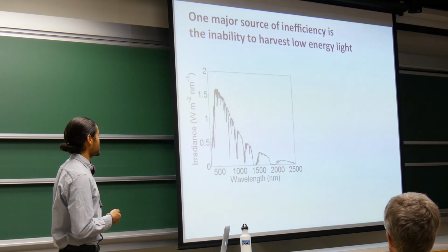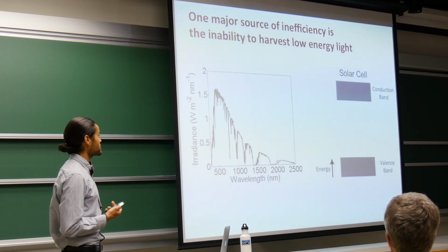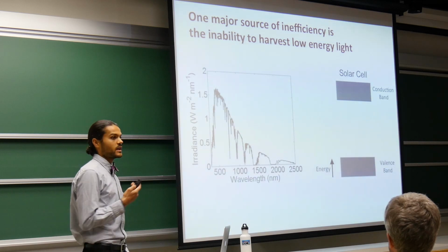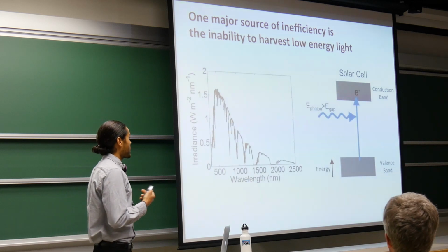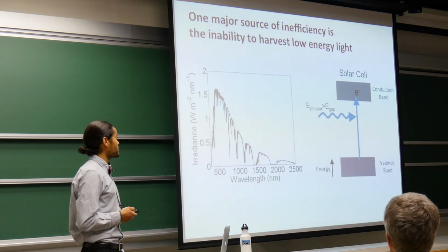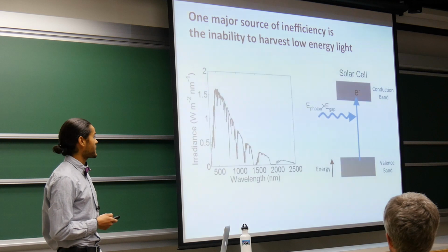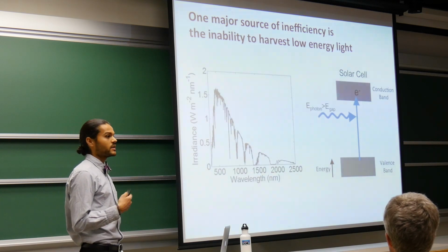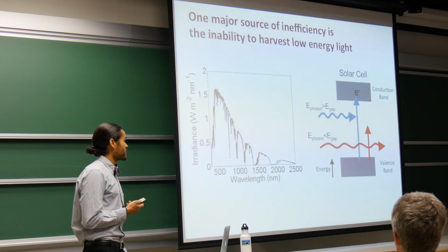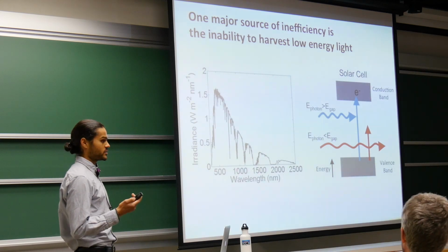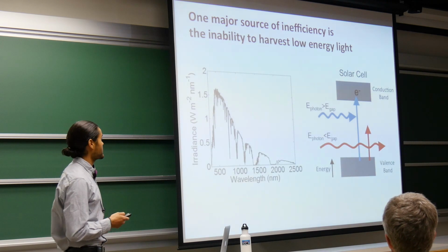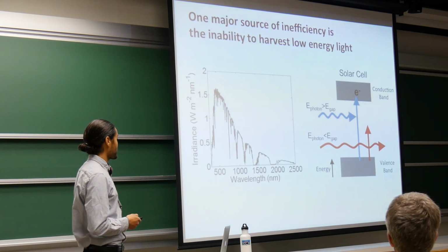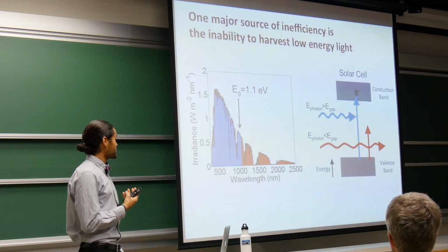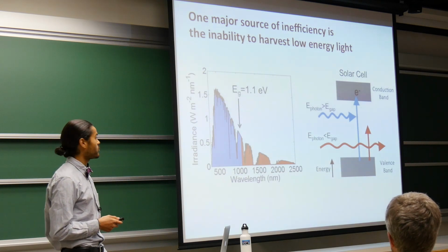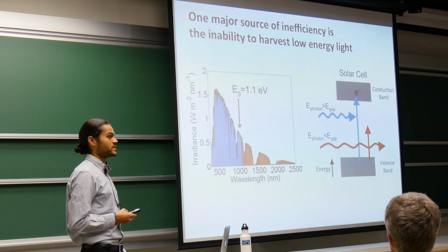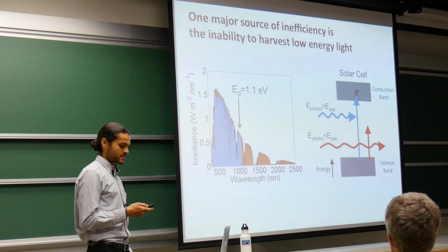And if we're trying to harvest this energy using a single junction solar cell, a conventional solar cell, which is characterized by a valence band and a conduction band separated by a band gap, what happens if we illuminate the solar cell with a photon that has energy greater than the band gap is that that photon can be absorbed by the solar cell and contribute to current. If the photon's energy is less than the band gap, however, it will simply be transmitted through the cell and will be wasted by this conventional solar cell device. So for a single junction solar cell like a silicon cell with a band gap of 1.1 electron volts, it turns out that this wasted energy amounts to about 25% of the energy in sunlight.